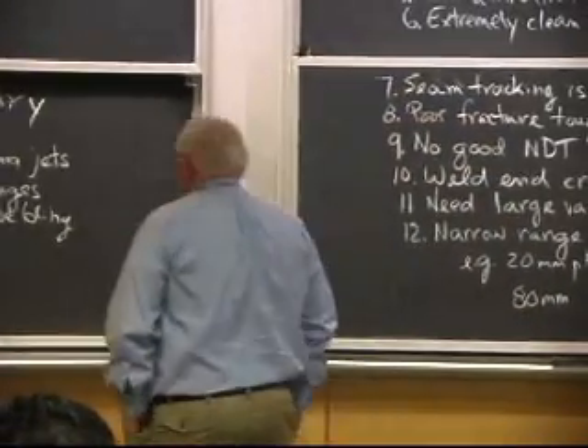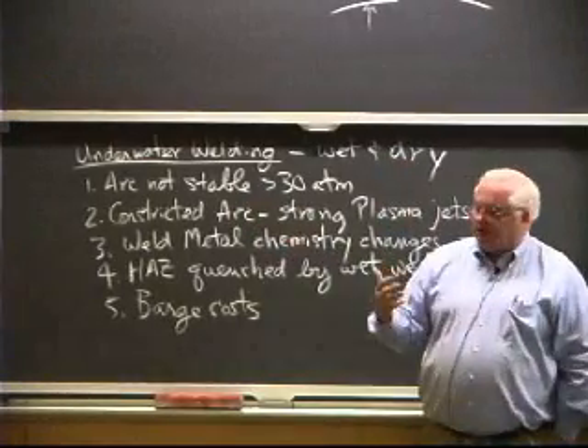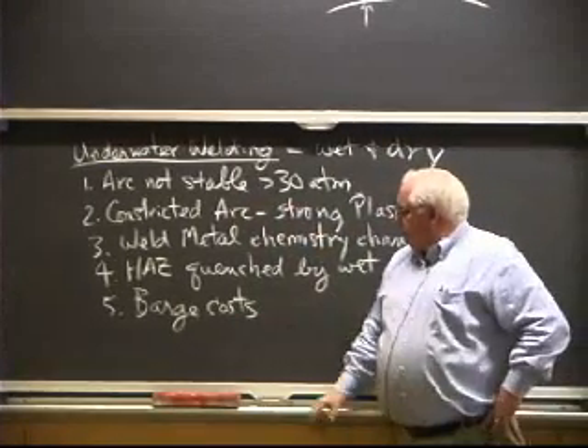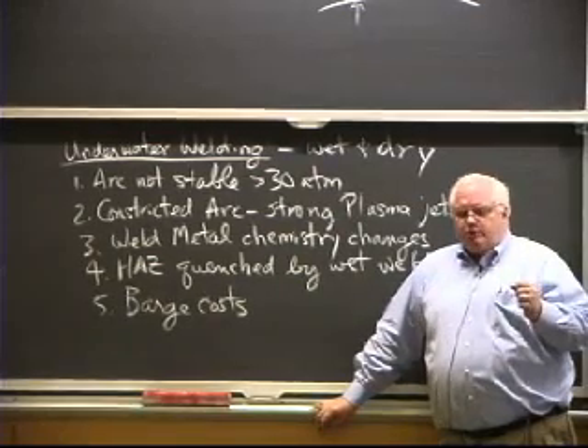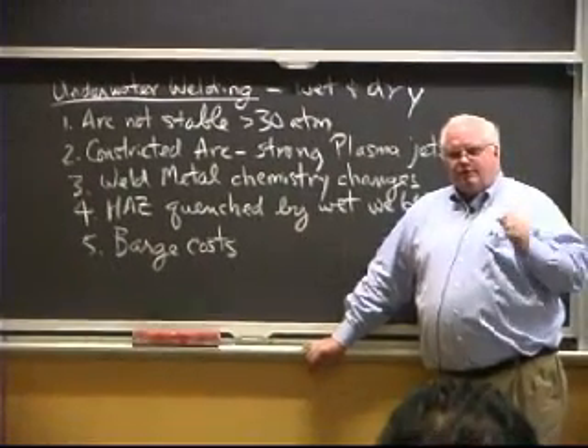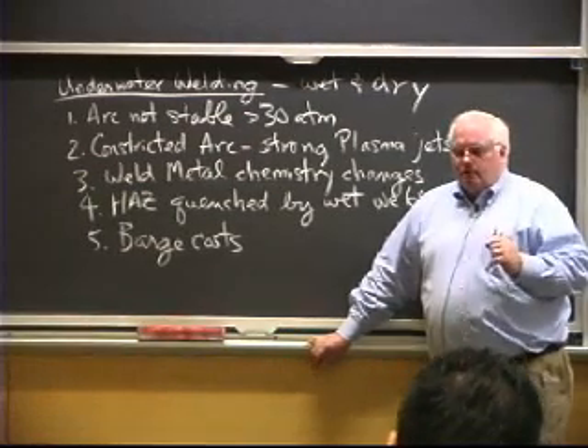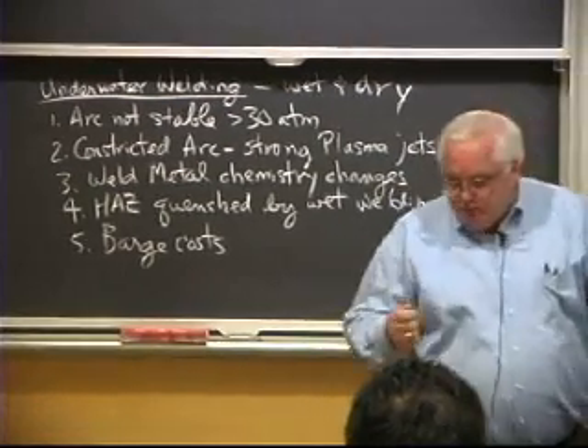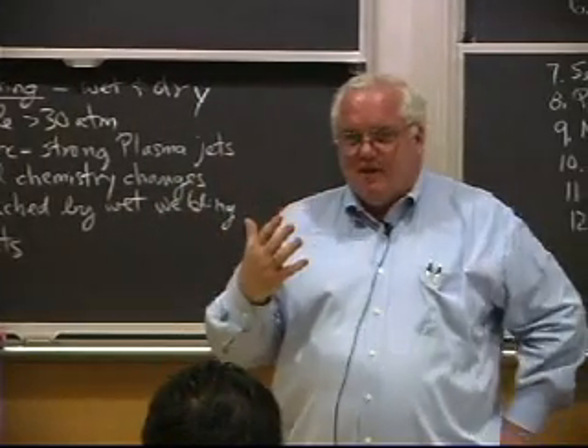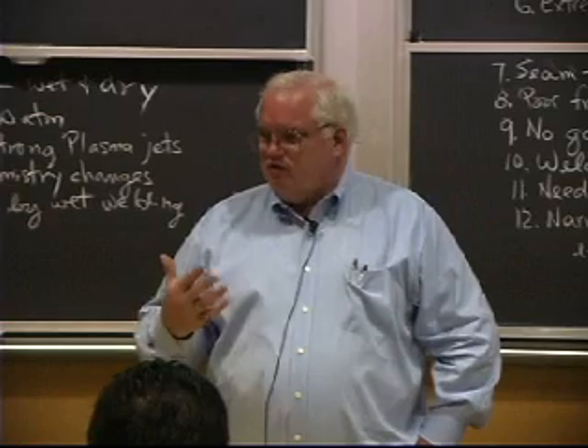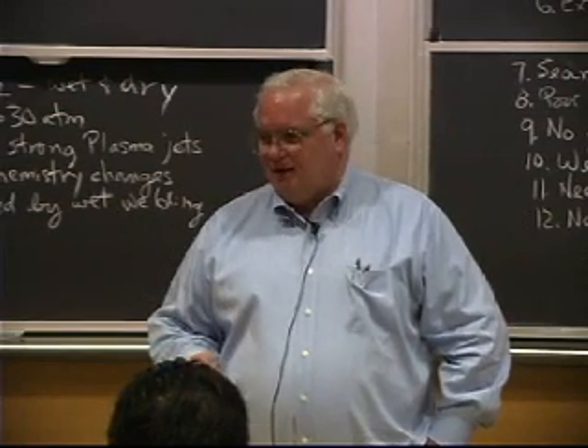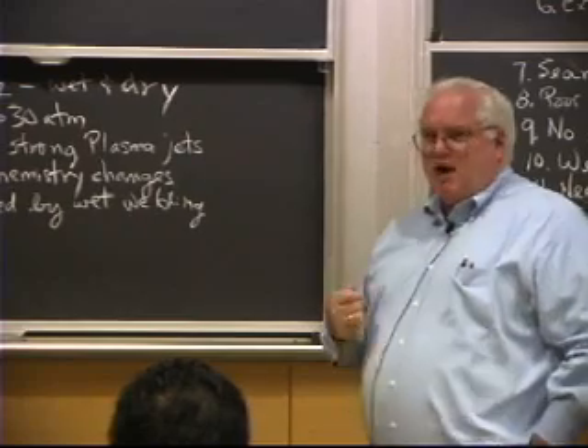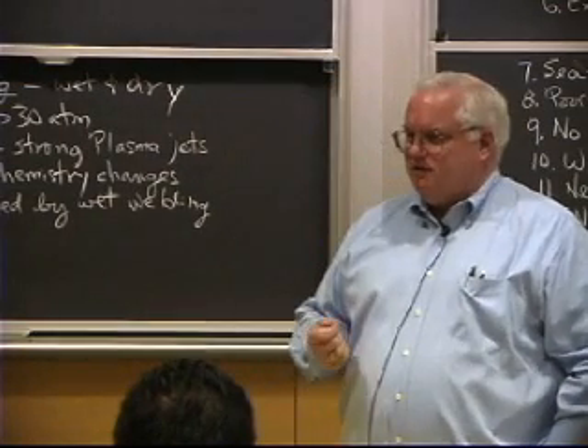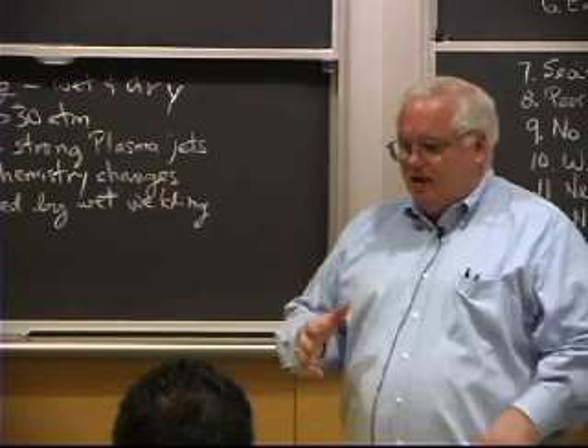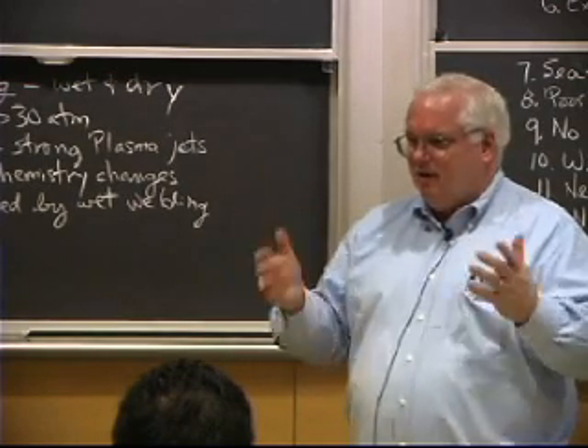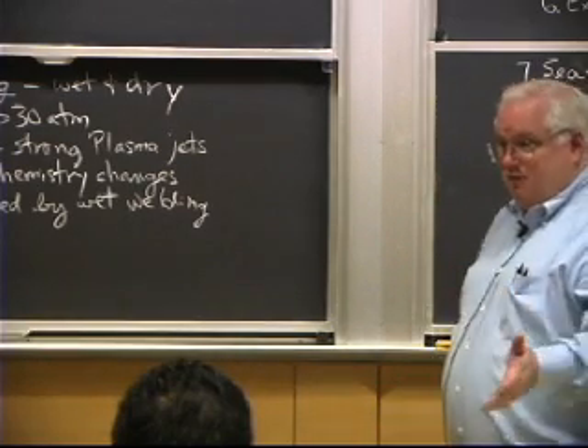And so it can be done. The problem is, well, the welding is different, and so it takes some practice. The arc gets constricted by the pressure, gives you stronger plasma jets. Stronger plasma jets means if the welder doesn't have some practice, some experience in that, then, well, first of all, if they're doing it wet, you're welding through bubbles, right? Not only do you have to have goggles on to keep from burning your eyes, but you're welding through bubbles, and you can't really see exactly what you're doing, okay? So it's sort of like a blind man welding. You can't really see the puddle with the same sort of clarity that you can see ordinarily. And all the smoke is getting into the water and clouding up the water. Sometimes the water that you're welding in is not very clear to begin with, right?